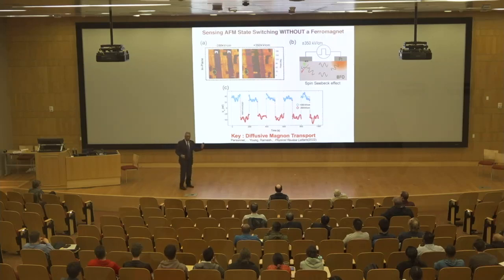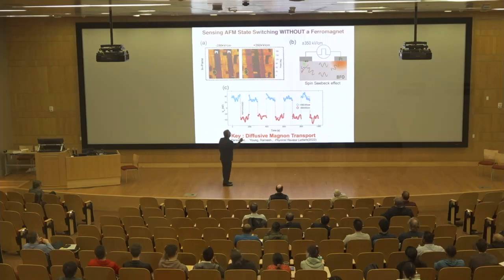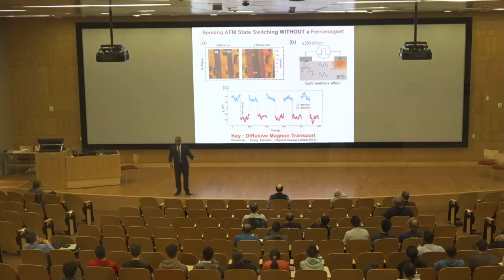Then we said, let us simply heat the platinum. And when you heat it, basically it starts to put out something called a magnon. These are just spin waves, okay? And you can then pick up that magnon as the inverse spin Hall effect using the other platinum. This whole effect is called the spin-Seebeck effect. If you're into spintronics, the spin-Seebeck and the spin Hall effects are very heavily studied right now.